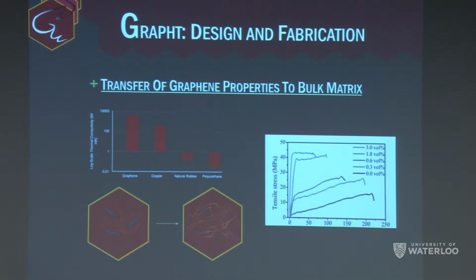Good homogeneity is important for almost all of your properties, especially mechanical properties such as tensile strength, shear strength, and abrasion resistance. But it's most important for conductivity properties such as thermal and electrical conductivity. In order to get sufficient conductivity by adding filler into your composite, you need enough of the filler to create what's called a percolation network that allows the conductivity to flow along the filler particles. Because Grapht is more easily dispersed in your composite, you get a higher effective concentration for the same weight loading, which allows you to achieve these conductivity values at a much lower original weight loading, keeping costs down.